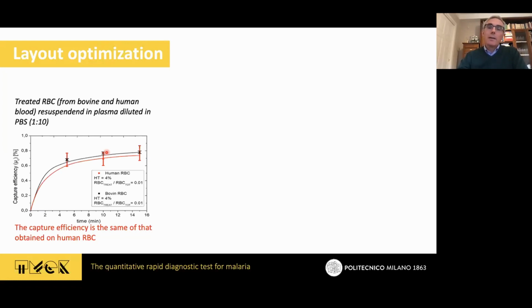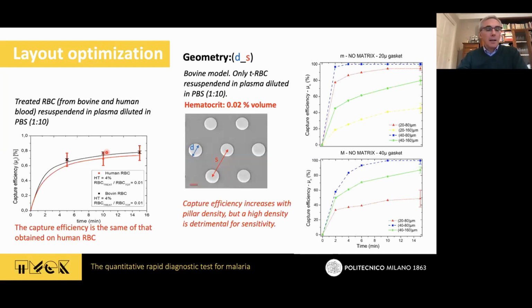So we have been working with bovine blood samples, and we optimized the geometry of our chip. Essentially, we chose an HCP, hexagonal close-packed, configuration, and we have been playing with the diameter of the pillars and the distance, and also with the height of the cell. Just to make a long story short, we decided to work with the configuration corresponding to the green curve, which means 40 micron diameter and 160 micron lattice parameter of our HCP lattice. The reason is that there are other configurations which are better, like the blue one, which corresponds to 40 micron diameter and a distance of 80, but the wiring of the electrode would become too complex when you have to think that we also have to put the electrode on top. So we decided to work with this one.